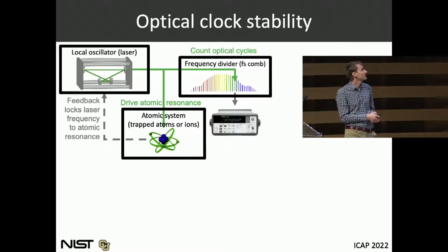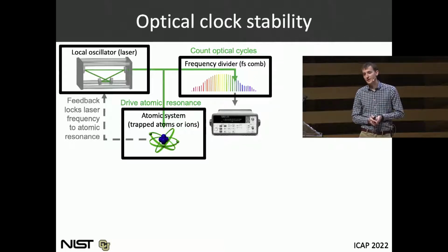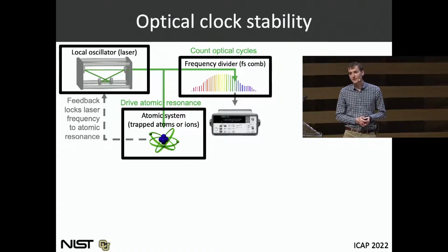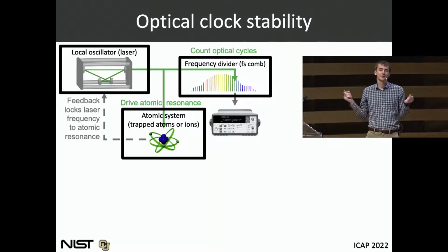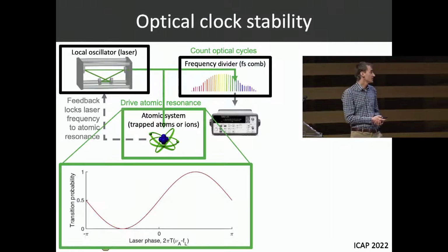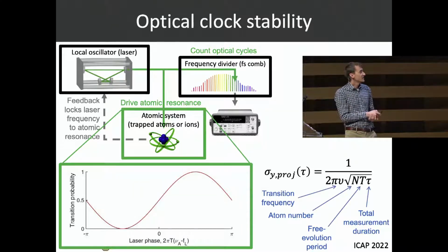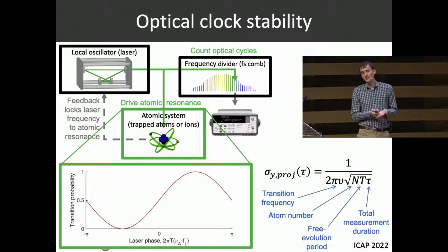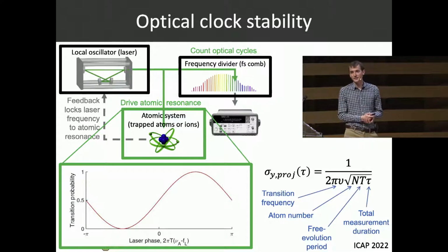And this is a technique specifically for comparing two optical clocks in which laser phase noise is made to be common mode so that it drops out. And in that way, we can extend the Ramsey free precession time to minimize the quantum projection noise. So here, this Ramsey free evolution time, big T, can be extended out to the excited state lifetime of aluminum, that 20 seconds I mentioned earlier.